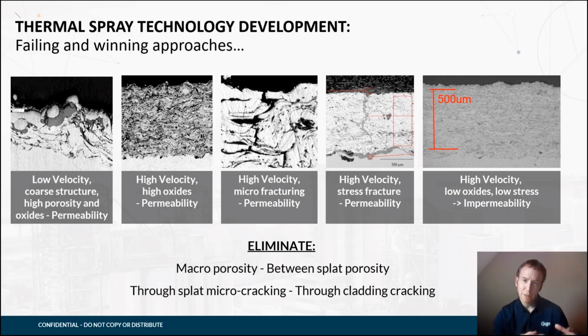So by using a high velocity system with a modified alloy, we eliminate these weaknesses which we'd seen previously in thermal spray applications in the field. IGS as a company, we've lived through all of these different stages, and we've used these processes and learned from these processes in order to develop the systems we use today. So in the early 90s, we moved from low velocity to high velocity. In the early 2000s, we moved from unmodified alloy to a modified alloy. And in each case, it was from field applications and premature failures of these systems in these types of corrosive environments. Since about 2000, we've been using a high velocity system with a modified alloy.